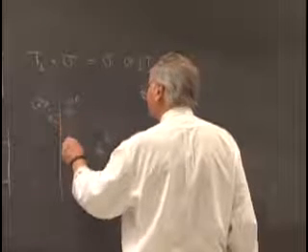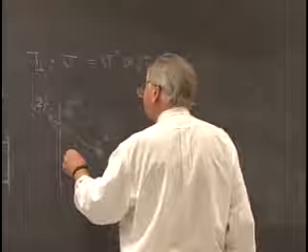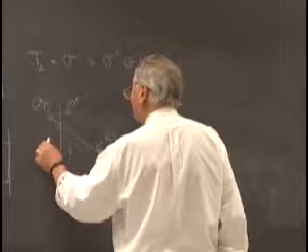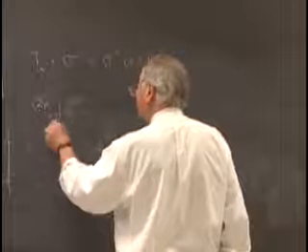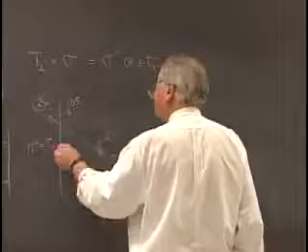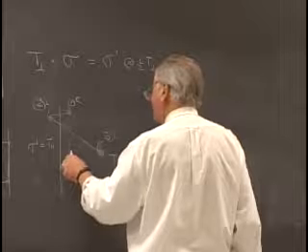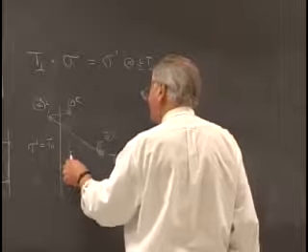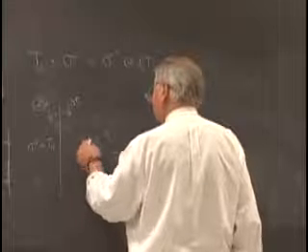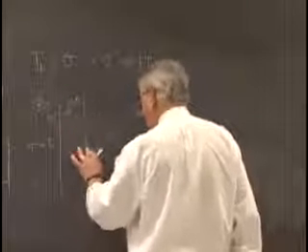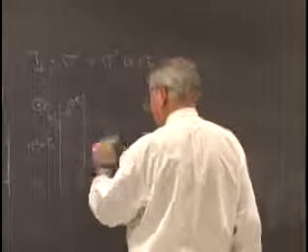We had to first translate down by the part of the translation, let me call it tau, which is equal to that part of the translation t which is parallel to the reflection operation, and then we had to reflect across, and that would get us from the first to the third. That was a new sort of operation. We'd indicate its locus by a dashed line to distinguish it from a mirror plane, and it has a translation part and a reflection part.